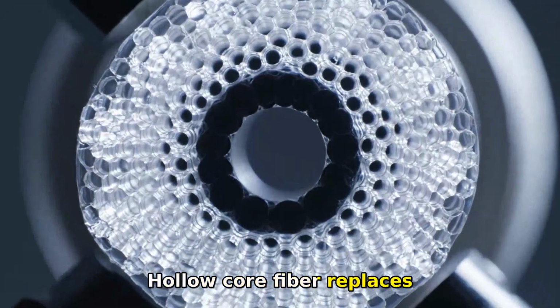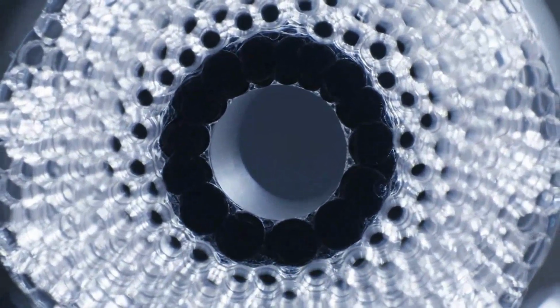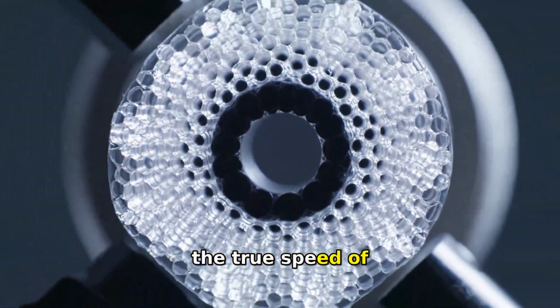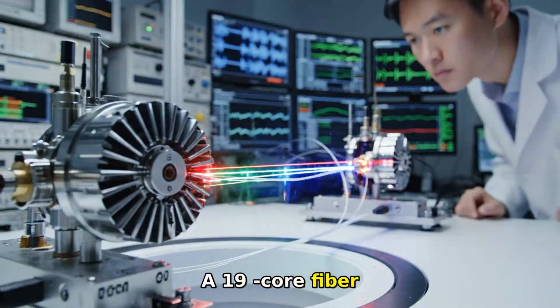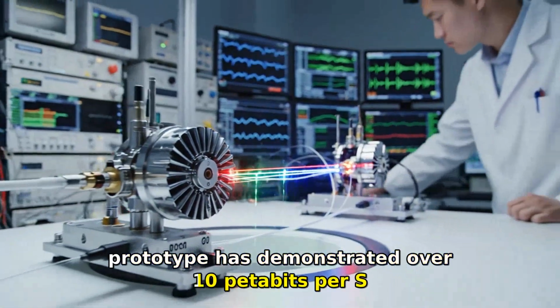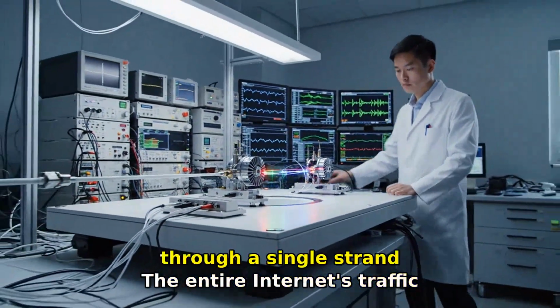Hollow core fiber replaces the glass core with air. Data moves closer to the true speed of light in vacuum. A 19-core fiber prototype has demonstrated over 10 petabits per second, the entire Internet's traffic through a single strand.